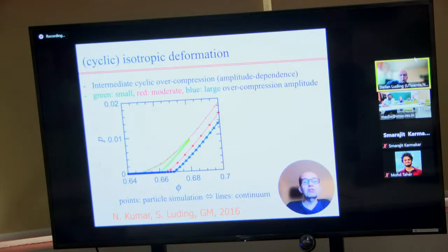Now let's take a look at stress versus density. We come from unjammed, low density, we compress up to a certain magnitude of density or stress, and then we go back. So the green line is going up to density, volume fraction 0.68, and going back. And this already shows that the jamming density at the beginning, at the loading, is not the same as the unjamming density at unloading. The red is going up to a much higher density and coming back. The red dots, big dots, are the back branch. The small dots are the loading branch. Big dots are unloading.